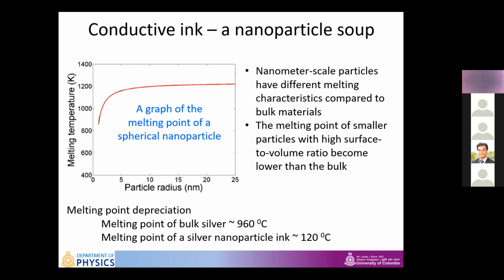Now, this reduction in melting point is ideal when dealing with heat sensitive substrates for electronics fabrication. For sure, we cannot heat the heat sensitive material too much to make the ink conductive. If we can reduce the melting point of the constituents of the ink below the damage threshold of the substrate, then we can safely heat up the substrate to make the ink conductive. So that's basically the one important key benefit of having nanoparticles. We can make the ink conductive without damaging the heat sensitive substrate.